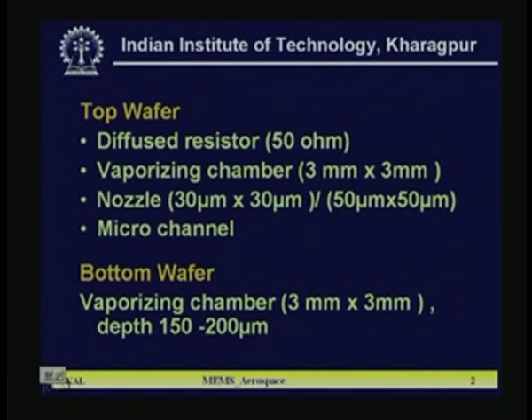Here, in the top wafer we use diffused resistors, we just fabricate diffused resistors of 50 ohms. The vaporizing chamber is 3 millimeter by 3 millimeter, the nozzle is 30 micron by 30 micron, micro channels will be there. The bottom wafer has a vaporizing chamber of 3 millimeter by 3 millimeter, and the depth will be 150 to 200 micrometer.